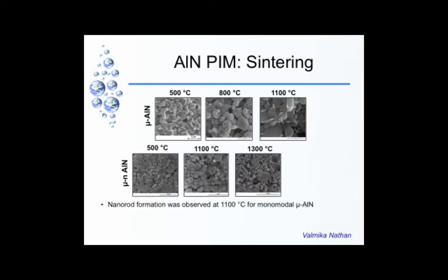With the micro-nano aluminum nitride, we ended up sintering this material to the point where around 1300 or so it begins to show a good amount of densification. You can see individual particles, and there are some necks, interconnections that are beginning. And there's maybe some dissolution of the aluminum nitride. That's possible. That's a good thing.